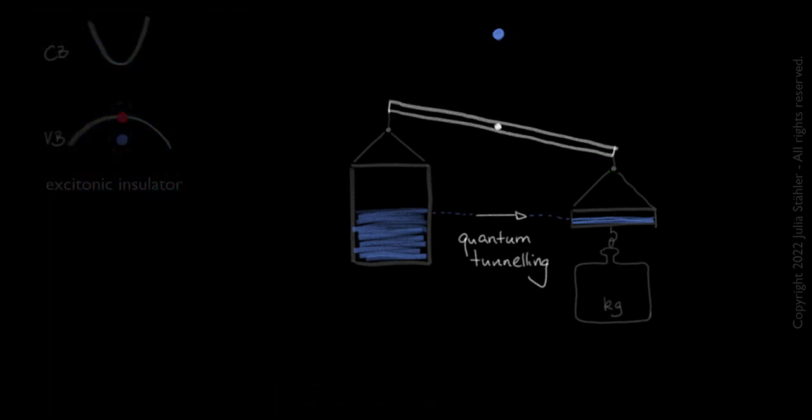We find that, after photoexcitation, the electrons do not return to the exciton condensate directly, but that they take a detour via the main reservoir, the valence band. They reach it after roughly a picosecond. Once they have arrived there, it takes a few to 60 picoseconds for the exciton condensate to stabilize.